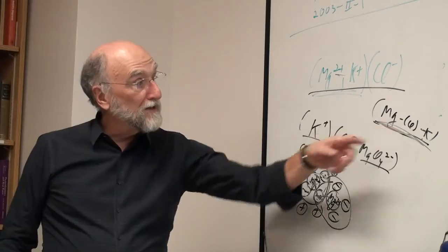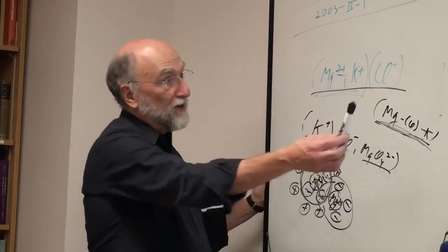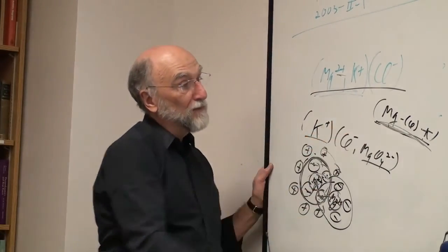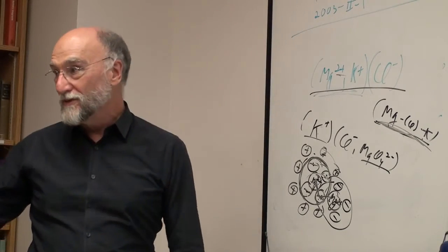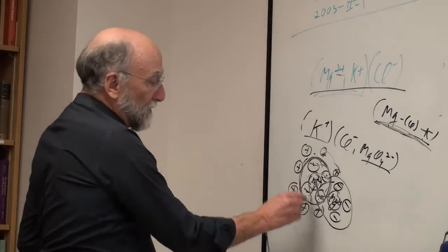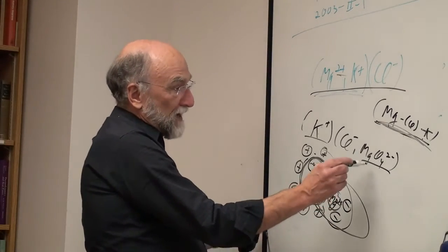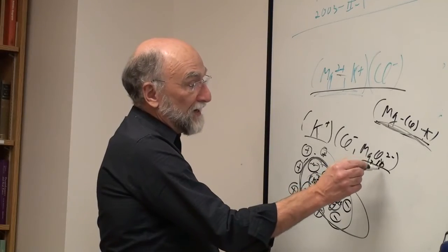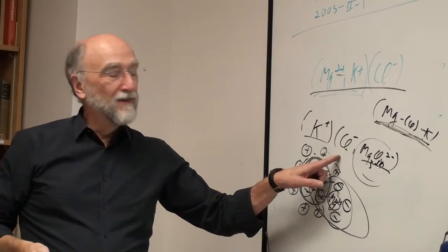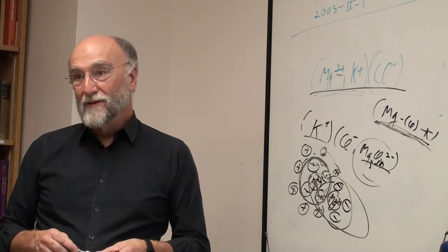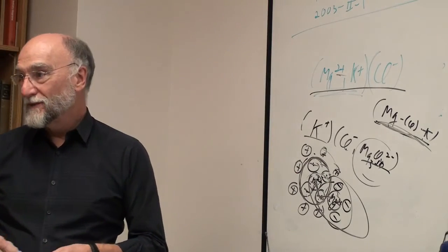Okay, but once you start getting into more concentrated solutions, the short-range ordering model becomes simpler mathematically than trying to mix your dimers and your trimers and your tetramers. And besides, if you get more than a dimer anyway, if you have something like Mg3Cl10, that's not going to substitute on one lattice with a little tiny chlorine. So it starts to get a bit screwy.